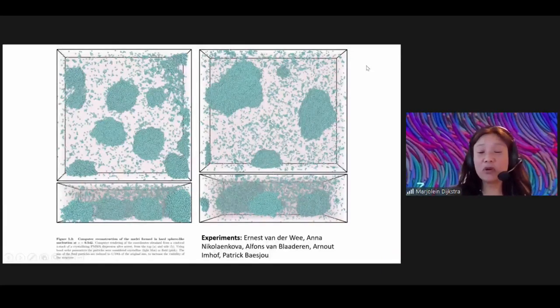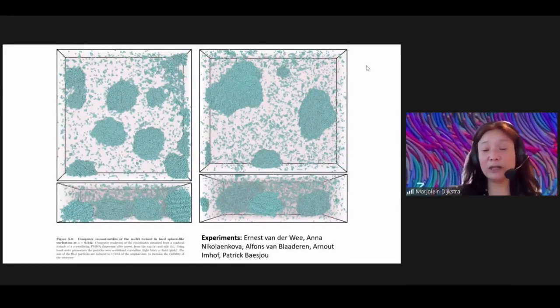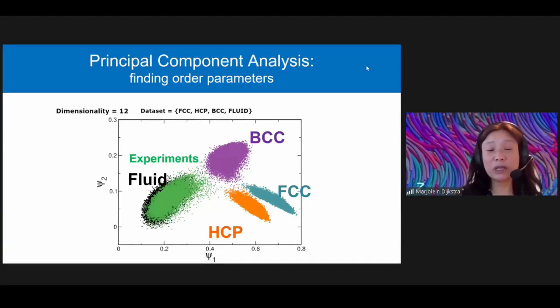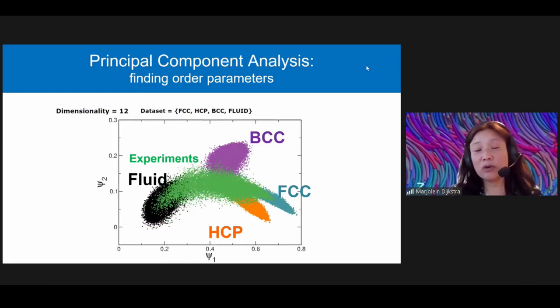We can do the same for experimental data. This is data from the group of Alfons van Blaaderen. They use a very nice trick in which they arrest the system by polymerizing the solvent, and then they can do that at different times in a nucleation trajectory and track all the particle coordinates. So they can start in the fluid phase, and if you do the same analysis that we did for the simulation trajectory, you can see that it nicely goes to the FCC phase.